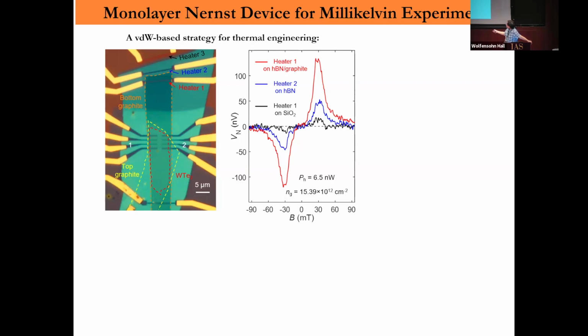So this is a device, and what I'm showing here is that if we apply this voltage, the Nernst measurements use these three different heaters: one on silicon oxide, another on boron nitride, and another on graphite. You see very different appearance, right?